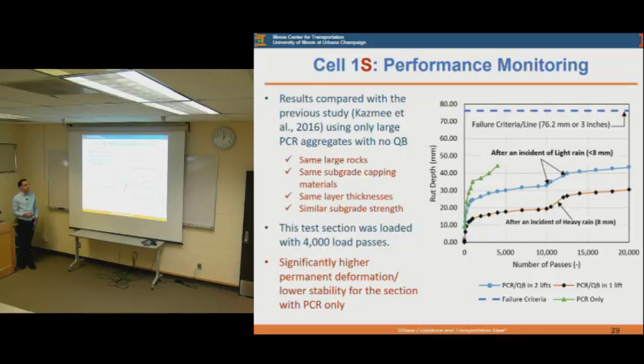And as you can see, those previous test sections had the same large rocks, the same primary crusher runs aggregate, the same source, the same capping material, the same layer thicknesses, and a similar subgrade strength, a CBR of 1. And they were constructed in almost the same location, in the Atlas yard here. But they had significantly higher rutting compared to the ones that had the quarry byproduct blended with the primary crusher runs, which shows that this is actually working, and it's actually reducing the rutting of these layers.